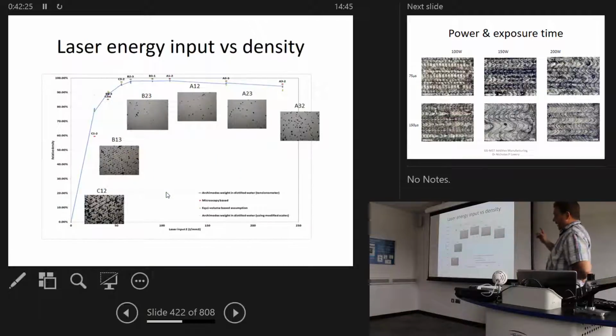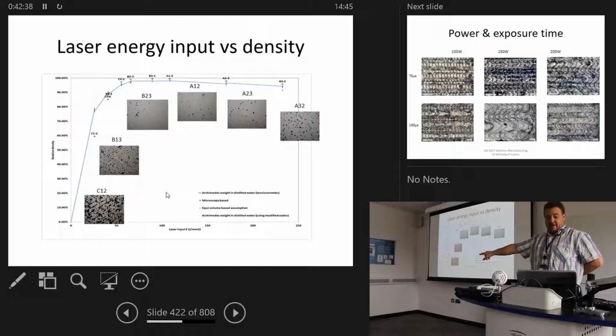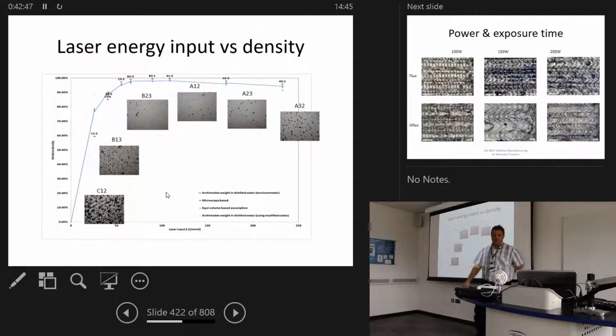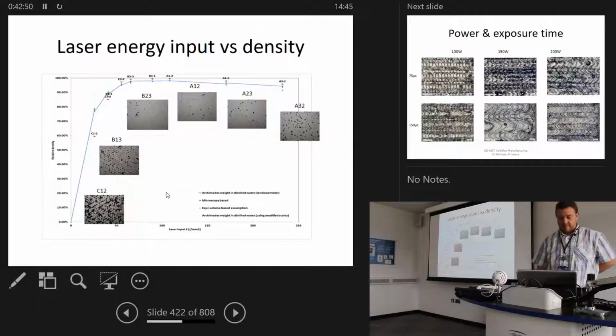It allows us to quantify, once we've actually built the parts, we can look at the microstructure, we can look at the porosity, so we look at that porosity there. We can also measure the density of the part. And you can see, for example, on this part, as a function of the energy density at the bottom, we can actually see that we find an optimal about B23, sample B23 and A12, and right at the peak density you can get, and after that we start to see the apparition of this other porosity, which is a sort of more rounded porosity.